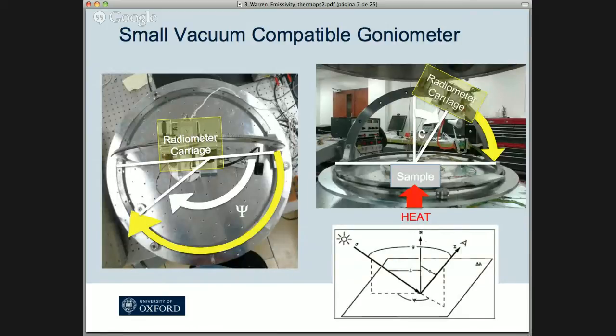But in the designs, we left room to put in an illumination arm, which we hope to add in the future. This whole goniometer is designed to fit inside a 1 meter radius vacuum chamber, to give you an idea of the scale of the thing. And then it's all surrounded by a cold shield, for two reasons. One is that we want to reduce the thermal background noise, and the second is to set up a space-like environment around the sample, so we can induce a thermal gradient in a powder sample.